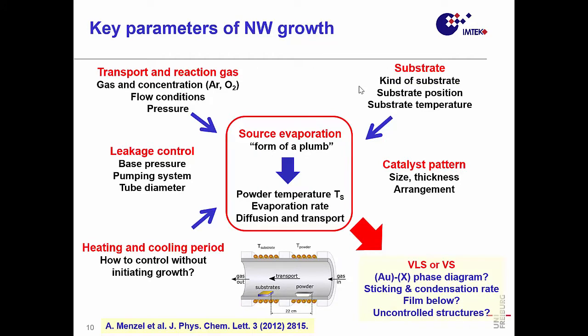If you do that in such a CVD system, which is normally a tube furnace, it depends how much money you have. If you have an MOCVD system, it costs $1 million. Not very often do people have that. If you have a tube furnace and control these with a quartz tube, you can do it in a rather easy way, but still you have to understand what kind of key parameters are controlling your growth of your nanostructures, and that means think deeply about what kind of parameters. I will show you some of these parameters and how they are affecting the growth. Leakage control is very important if you're growing oxide-related materials. You have to also think about substrate, catalyst pattern, and so on.